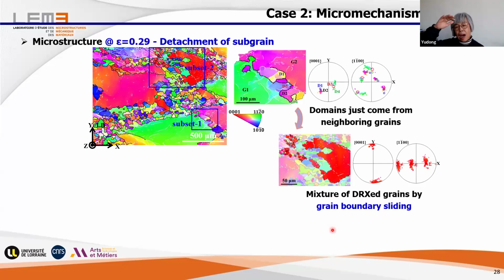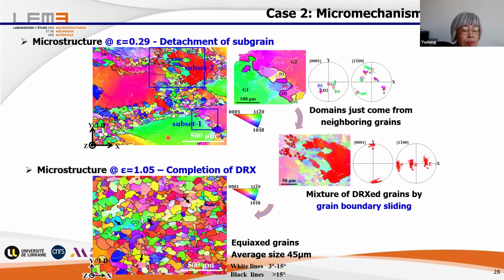That means either upper layer grains or lower layer grains, they will force in and separate the fragmented part from their mother grain. And with these, we have these boundary regions full of small grains. And now, if we continue our deformation to the final deformation, we see the completion of this, the whole part recrystallized, all microstructure recrystallized. And with all these analyses, we can say clearly this recrystallization is a continuous dynamic recrystallization.